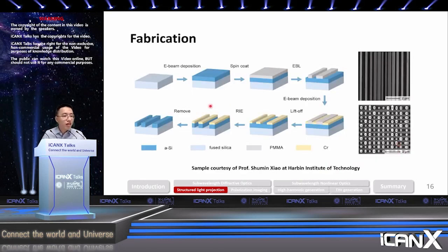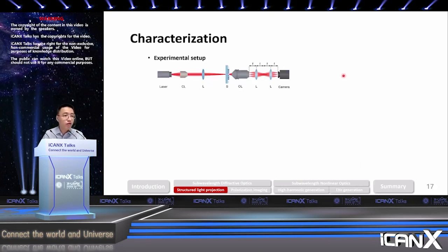For the device fabrication, it's based on very standard semiconductor fabrication processes using EBL lithography and etching. This sample was fabricated in collaboration with Professor Xiao Shumin's group at the Harbin Institute of Technology in China, and you can see the features look pretty nice. Then to characterize our sample, we built a simple Fourier imaging setup so that we can capture how the diffracted light looks.